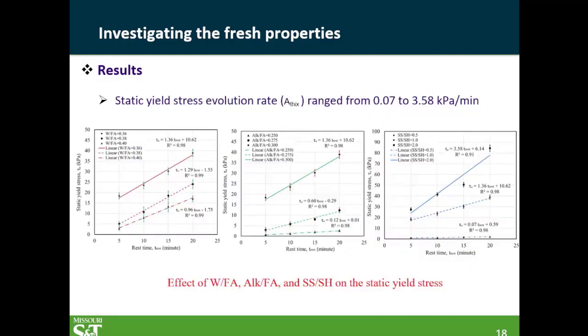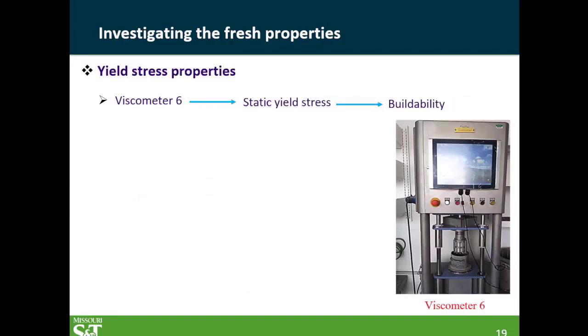And then we look at, for different rest times, what we call the static yield stress over here. And we found really a very nice linear correlation for the different mixtures. And then we would like to see if what we did here can be correlated to more rigorous testing.